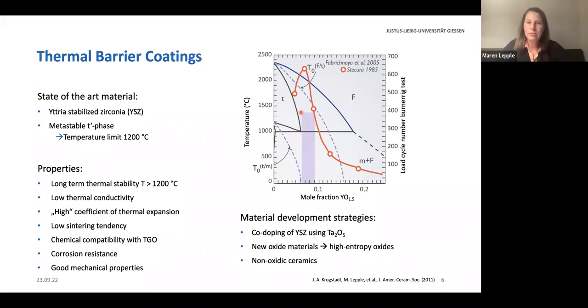However, it's not so easy to find new materials because the new materials have to meet a lot of requirements concerning the properties. So besides having a long-term thermal stability above 1200 degrees centigrade, they have to have a low thermal conductivity, a quite high coefficient of thermal expansion, so high for ceramic materials. They have to have a low sintering tendency, chemical compatibility with the alumina, so the thermally grown oxide, good corrosion resistance, and also good mechanical properties.